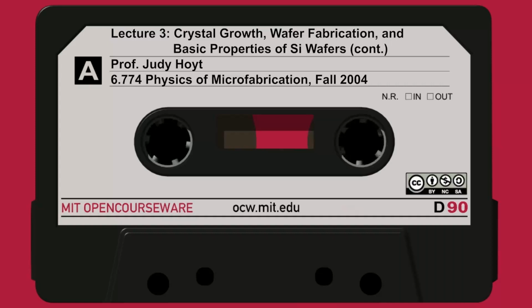It turns out surface processes are a dominant way of creating these point defects. For example, we can have generation and recombination of vacancies or interstitials at the surface, and they may create only 1 type. Again, this is a schematic, meant to be a cross-section of a lattice. Imagine up here is the top of my lattice. Above it is free space.